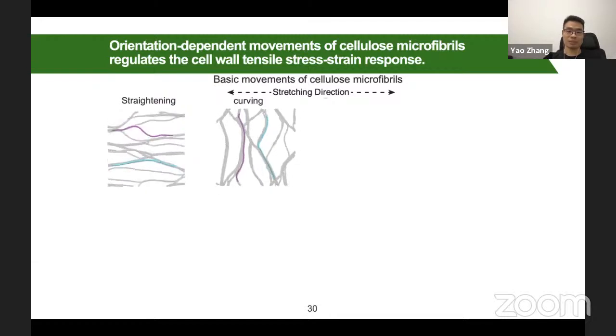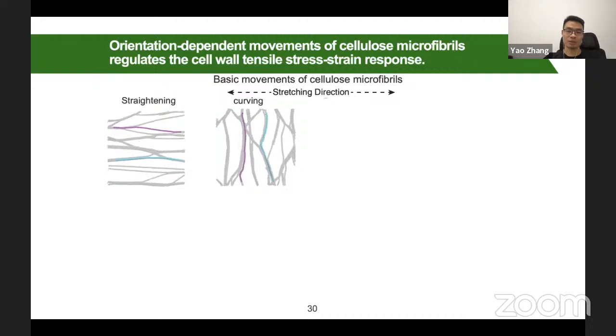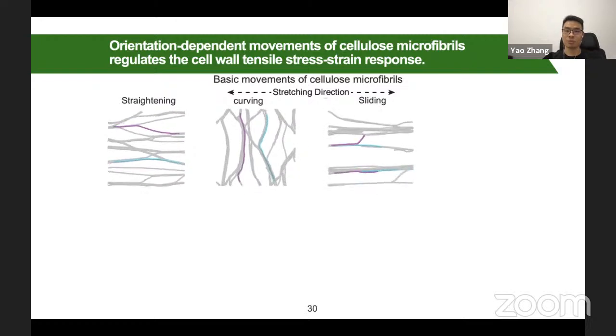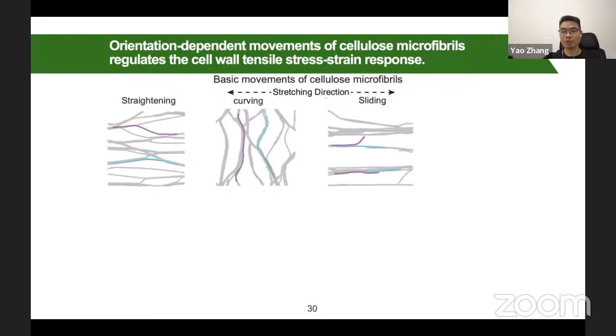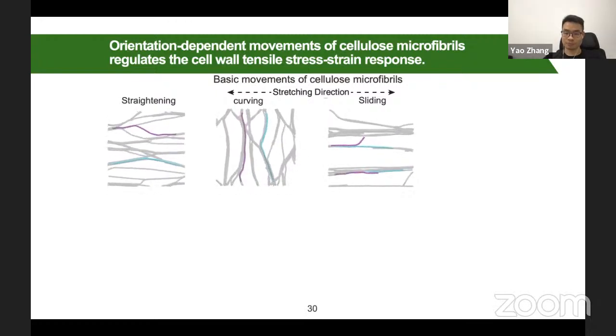The second one is curving, which is opposite of this straightening. If you look at this, the fibers have an orientation which is perpendicular to the stress direction. The third one is the sliding. That means that you have this cellulose fiber bundle, and within the bundle, one fiber begins to slide over another fiber.